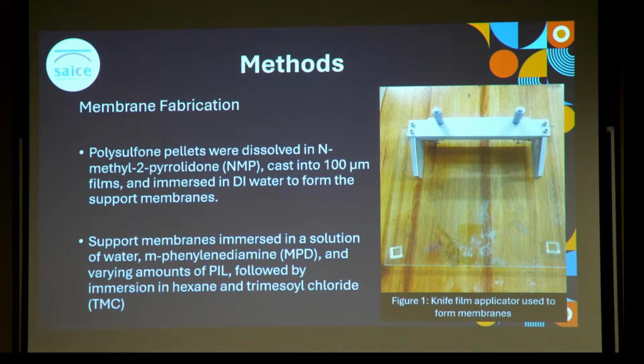The first step was carried out by dissolving and mixing polysulfone pellets in N-methyl-2-pyrrolidone. This solution was then poured onto a glass plate, and 100-micron films were cast using the casting knife film applicator shown on the screen. To form the active layer on top of the support membranes, these membranes were first immersed in an aqueous solution of m-phenylenediamine, and then in an organic solution of hexane and trimesoyl chloride.